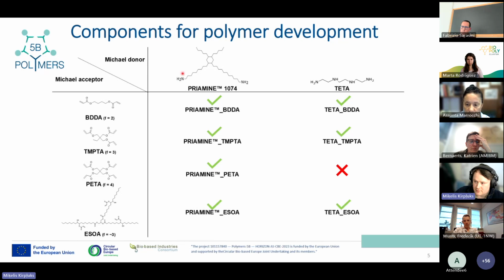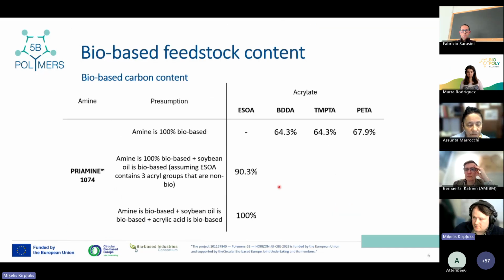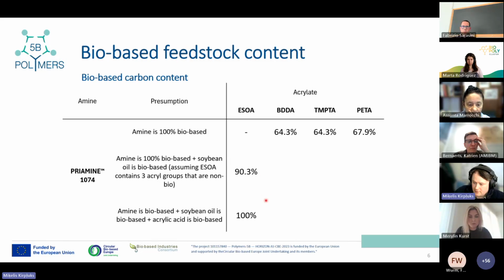And this amine was cured with different types of acrylates with different functionality. As a bio-based acrylate component, we used a soybean oil-based acrylate with an average functionality of 3. When we combine these bio-based components, the biocarbon content in the end resin or elastomer is 90.3%. And if we assume that the acrylic acid in the soybean oil-based epoxide is also bio-based, then we have 100% biocarbon content in the end material.